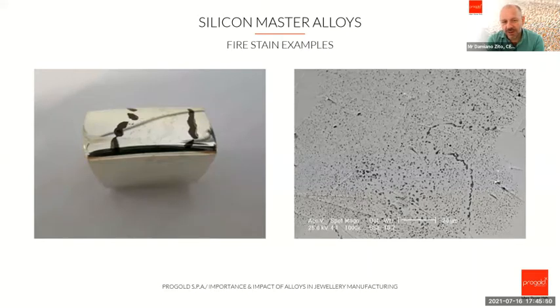but then the galvanic is not really sticking very well over copper oxide, and so this is very, very strictly connected with silicon, of course, with many other factors, but silicon alloys usually are able to reduce this problem very much.